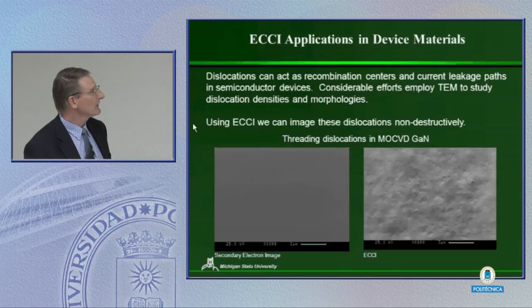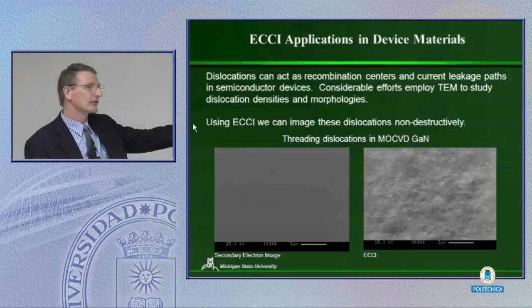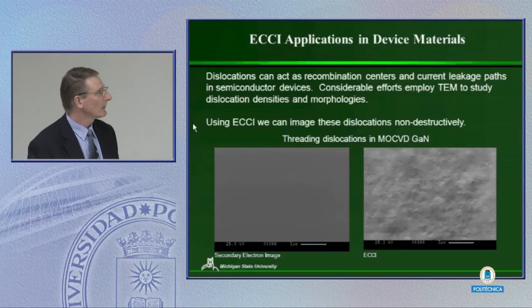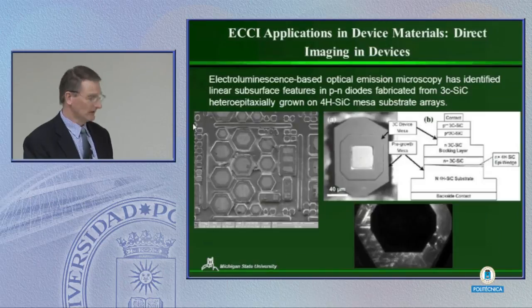This is a MOCVD gallium nitride. These are threading dislocations. Again, here's a secondary electron image, extremely smooth surface, but we get lots of threading dislocations coming through. And so this gives you the ability really to map where the dislocations are quite easily. But what we want to do is see if we could apply this a little bit more broadly.